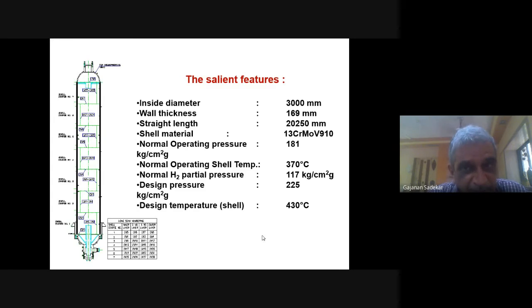The normal operating pressure of this equipment was 181 kg per centimeter square, and the hydrogen partial pressure, this number has a very significant meaning, was 117. While choosing the material, there are standards available. You might have heard of the Nelson curve, which tells you, based on the pressure and the temperature, what material to be chosen. So there are some guidelines available.